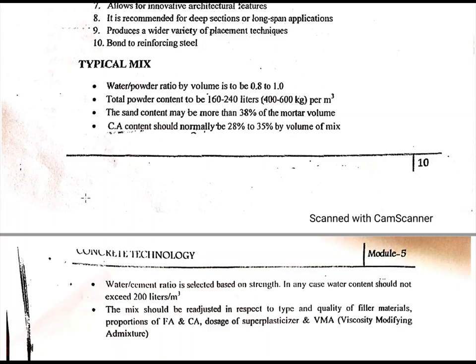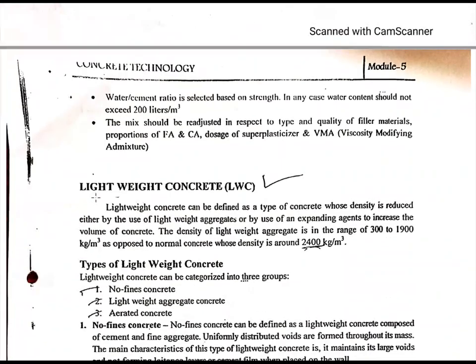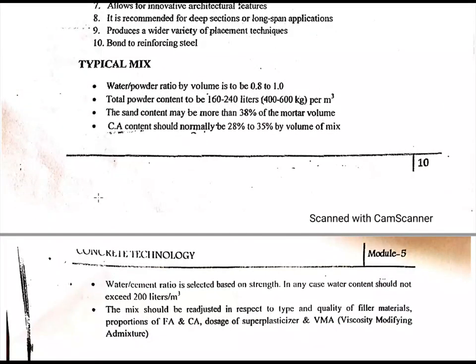The sand content may be more than 38% of the mortar volume. Coarse aggregate should normally be 28 to 35% by volume of mix. So here we have two more points. Water cement ratio is selected based on strength. In any case, water content should not exceed 200 liters per meter cube. We should not use more water than 200 liters per meter cube, thinking to increase workability or increase setting time.